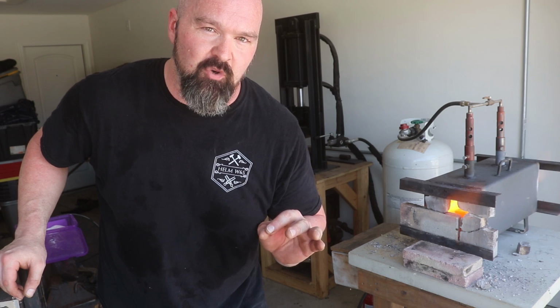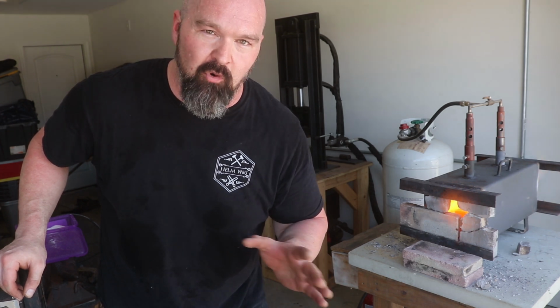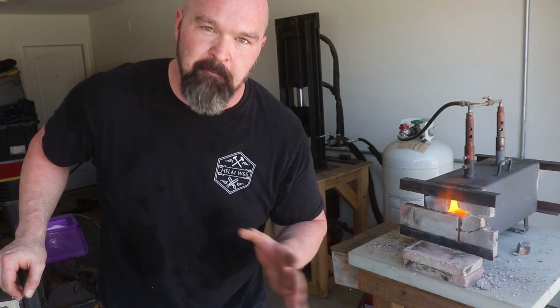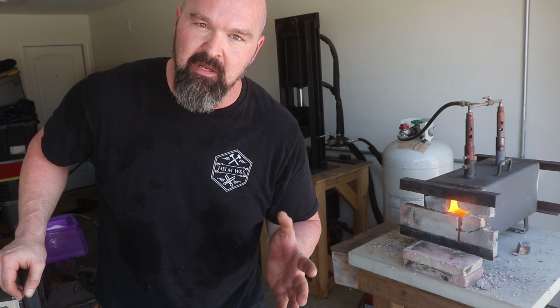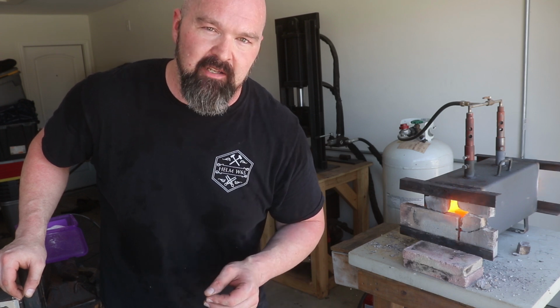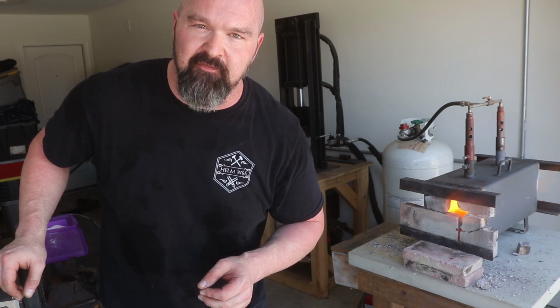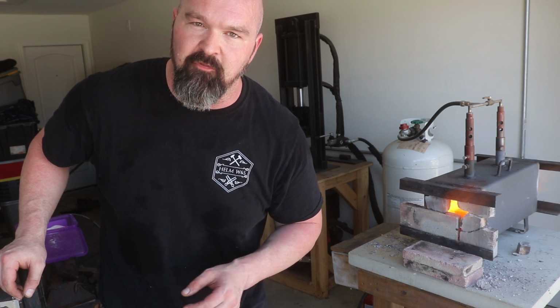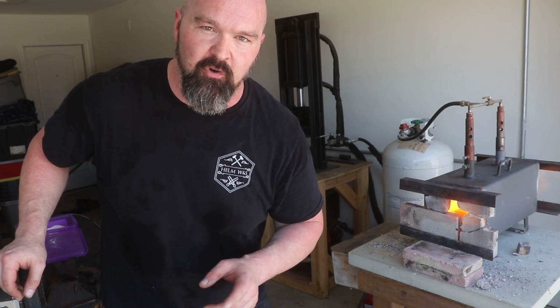Once it hits that temperature, you want to let it soak. Depending on your forge, this could be as long as 10-15 minutes. And also that depends on the size of the billet. This is a pretty sizable billet, so once it gets up to temp, I'm going to let it sit for about 6-7 minutes before I take it out and stick it in the press for the first welding heat.